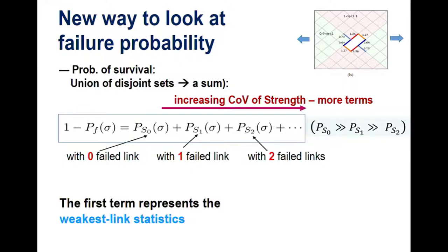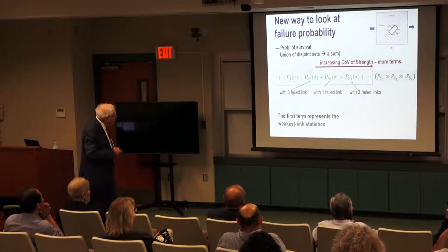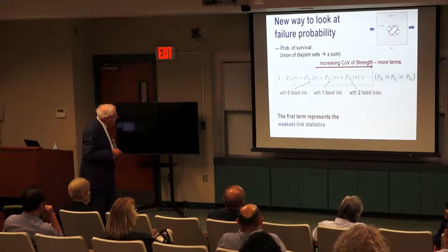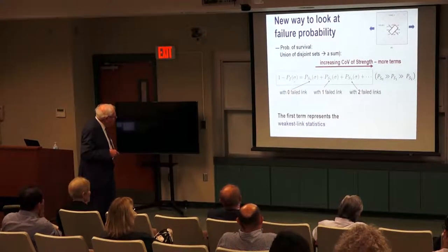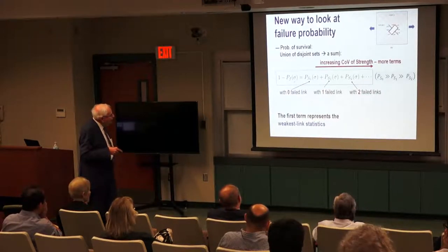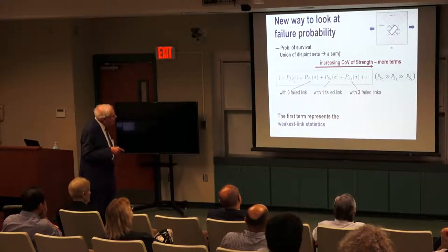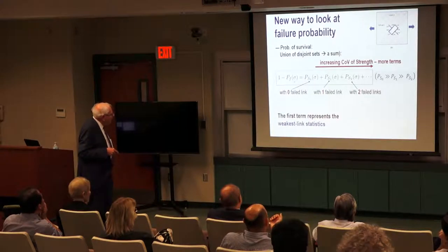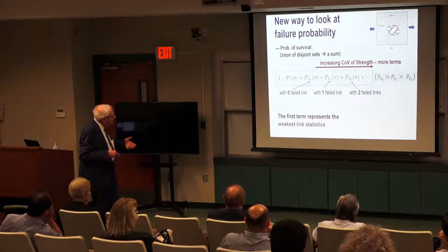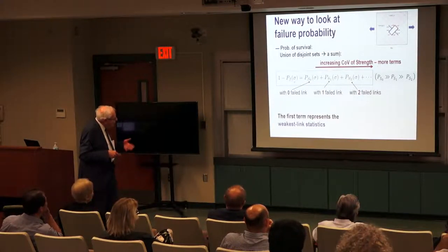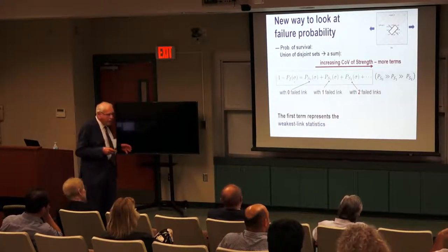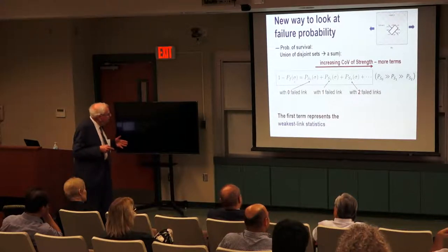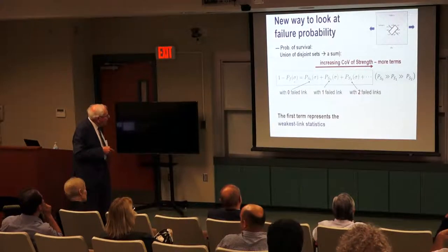Now, how to approach it analytically? So, differently than the Weibull distribution or fiber bundle, we consider survival probability, which is 1 minus failure probability, and this would be a sum of a number of terms, where this corresponds to survival with zero failed links. It means it fails when the first link fails in the fishnet. One link fails here, and there is a redistribution. This has higher stress, more stress, then it goes to no redistribution of stress. Now, then there are cases where one link failed before failure. It means failing as a second link. Then there is this distribution where it survives with two links and fails as a third link. So these are events which are disjoint, independent elements. It's really, in probabilistic terms, a union of disjoint sets. And that proves it must be a sum.